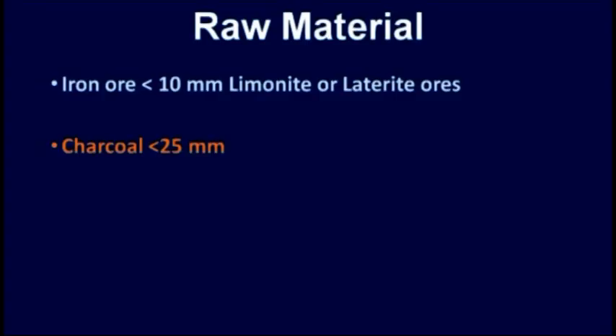The raw material was taken from open cast mines, not going deeper, and for charging into the furnace, the size was maintained around 10 mm. The iron ore was basically laterite or limonite. Charcoal was prepared locally, and the size of charcoal was maintained around 25 mm, 2.5 centimeter.